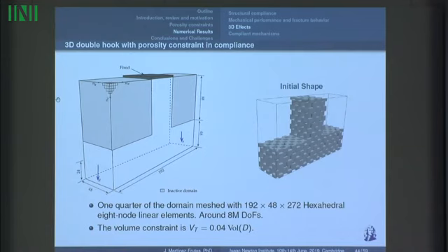So in the second example, I'd like to show you some 3D effects that appear when we introduce this formulation in a 3D example. So we want to analyze the impact that the porosity constraint has in the design in 3D, and it is expected that this impact is in regions with very small features. So we need to mesh this domain with a high resolution mesh. So we use 2.5 million elements that give us around 8 million degrees of freedom, and also we are going to use a very small volume constraint in order to have these very small feature sizes.